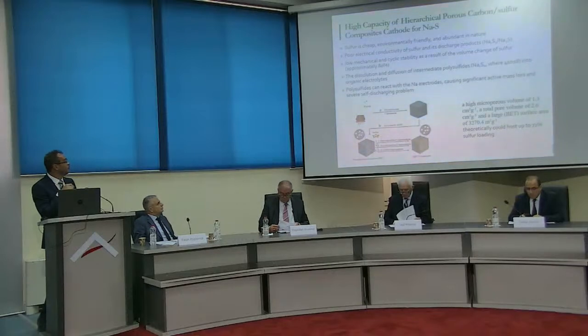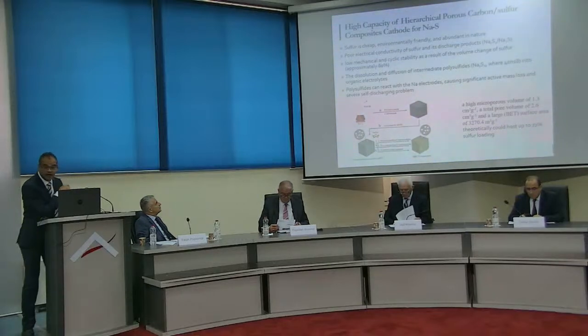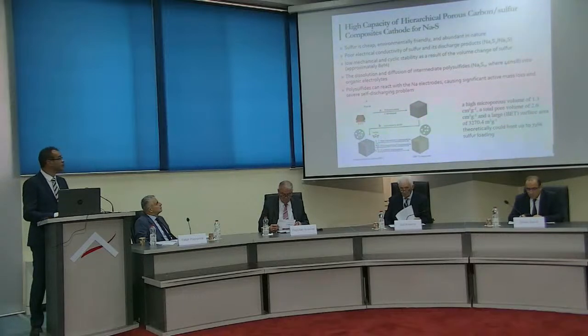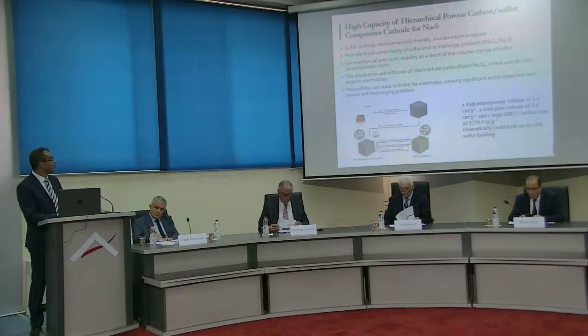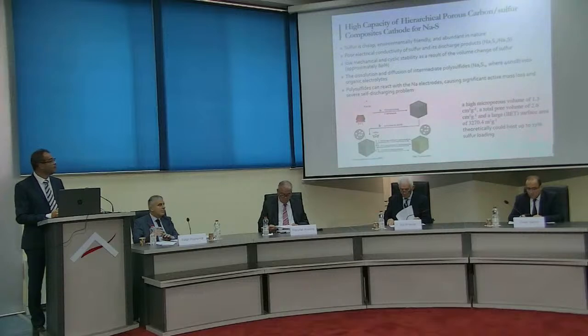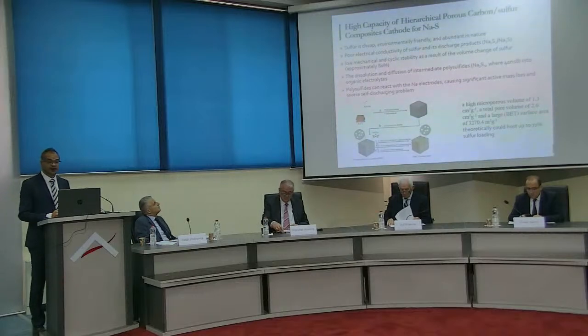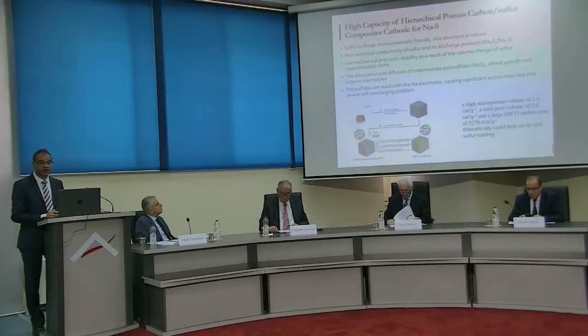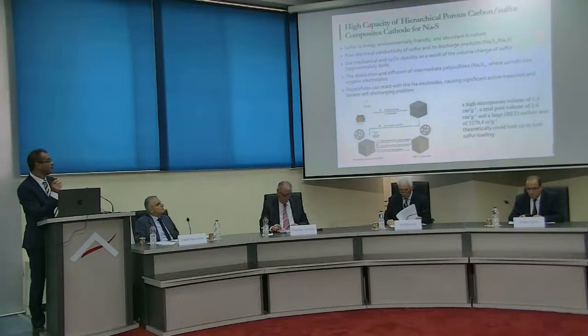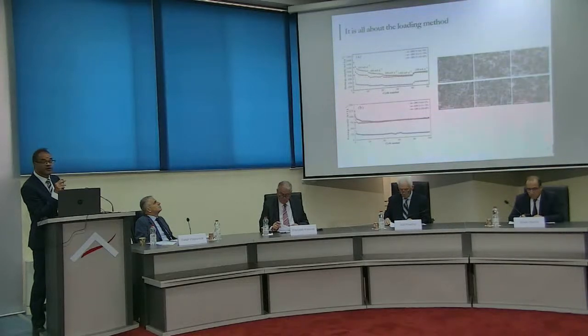This is one of our works for sodium sulfur, and we do work a lot on sodium sulfur, particularly regarding molten salt batteries, because that's where we come from. And this is a design basically where we loaded the sulfur into a porous sponge-like structure made of graphene, or made of graphitic material from polymer sponge, normal polymer sponge. We did it even with a kitchen sponge, like the normal kitchen sponge. We polymerize it, we graphitize it and fill it with sulfur, and it always depends on how we load the sulfur into the carbon.